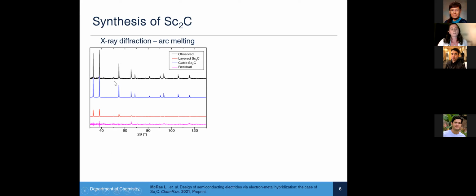And you can see in my observed diffraction pattern of the product, we have a small peak at 50, indicating that we do have some of the layered phase present. However, after doing refinement, we found that the layered phase made up less than half of the product, which was surprising given that it's the thermodynamically favored phase. We hypothesized that because arc melting has a rapid cool down process, we might have kinetic trapping of carbon and be favoring the cubic, more disordered phase over this very ordered layered phase.